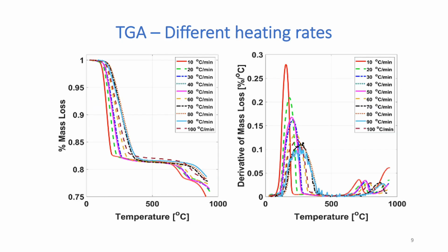Here, the TGA results are shown for different heating rates. So the mass loss is plotted as a function of temperature, and on the right hand side we have derivative of mass loss as a function of temperature. At lower heating rates, it gets more time for the same temperature difference, thereby showing a larger mass loss.